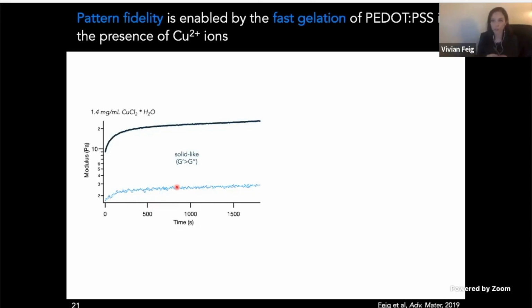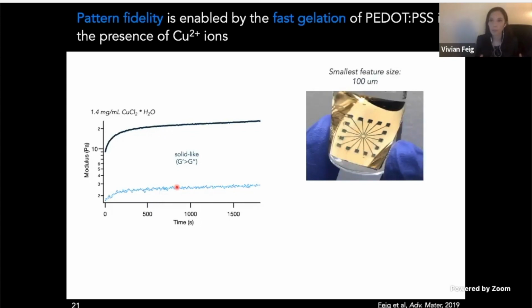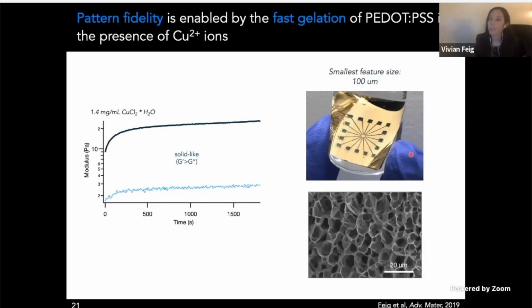And so combining this fast gelation with our sacrificial strategy, we now have a really simple way to create high resolution features like this shown here, where the smallest feature lines are 100 microns in width. But not only that, because the way this gel is formed is just through aggregation of these microgel particles, we can still maintain the high porosity and high water content that we need to get our desired mechanics.